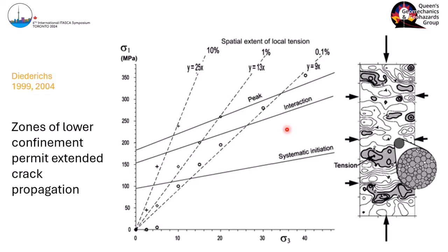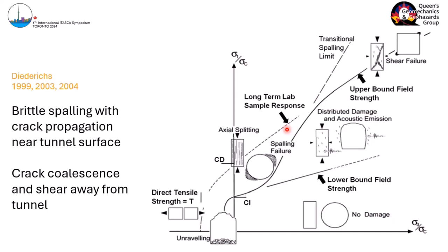This is almost increasing logarithmically, and you can see that around sigma 1 over sigma 3 of 20, 25, we're up to 10 percent, and then if you continue this, it basically envelops the sample. Meaning, if you're in this zone, you not only have accumulation of cracking, but you also have extension of the cracks, propagation of larger cracks happening, which then can have a much higher probability of interacting or just extending. And that all summed up led to this figure, where we divided the world into tension, spalling, and everything else.